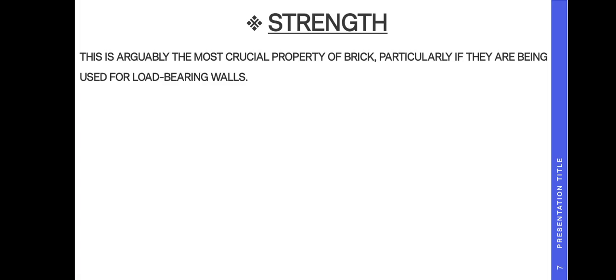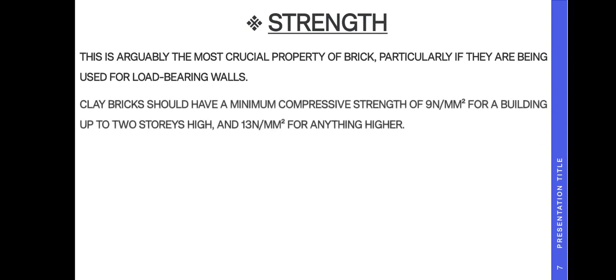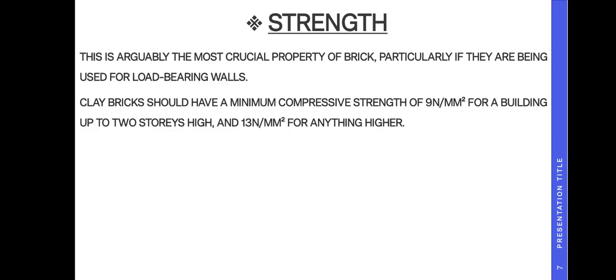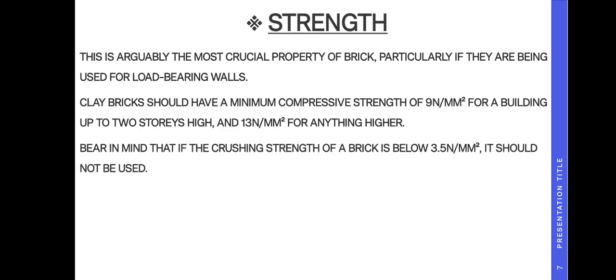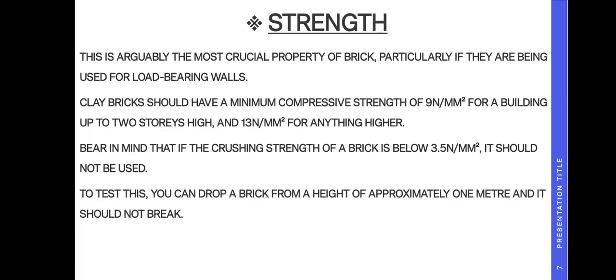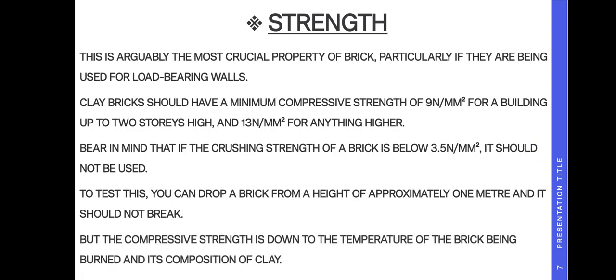Strength of the bricks is the most crucial property, particularly if they are being used for load-bearing walls. Clay bricks should have a minimum compressive strength of 9 N/mm² for buildings up to two stories, and 13 N/mm² for higher buildings. Bear in mind that if the crushing strength of the brick is below 3.5 N/mm², it should not be used. To test this, you can drop a brick from a height of approximately one meter and it should not break. Compressive strength is also dependent on the temperature at which the brick is burned and its clay composition.